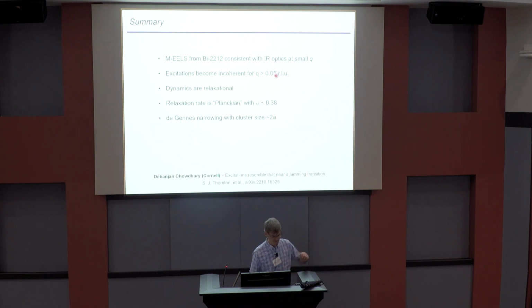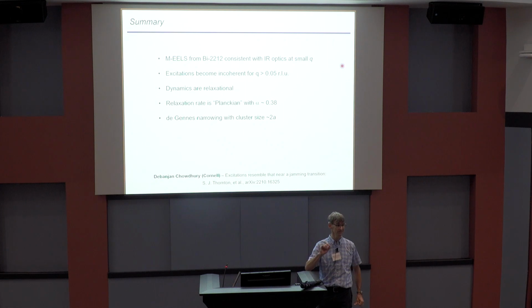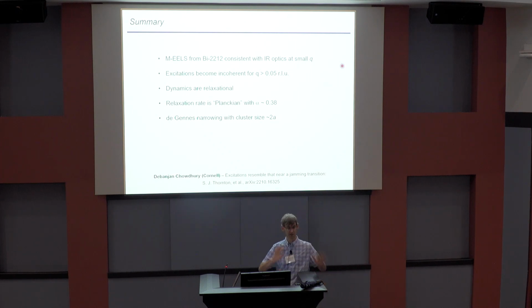In summary, we've been doing surface EELS, and at small q, all the probes seem to agree. There's a nice plasmon. It has to be there because it's a charged Fermi liquid, so the collective mode is gapped. It's up at high frequency. It's not like cold atoms where they're neutral, so everything's gapless. But all the measurements seem to be consistent. But at wave vectors larger than about 0.05, the excitations become incoherent, and you get a continuum. And this continuum is frequency independent at large frequency, up to a cutoff of an EV, which is a ridiculously high energy scale for a solid.